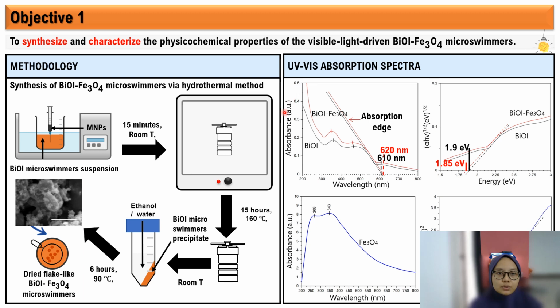This figure shows the absorption spectra of BiOI microswimmers and BiOI-Fe3O4 microswimmers. It can be observed that both microswimmers absorb in the visible light range, with band gap values of 1.9 electron volts and 1.85 electron volts. Meanwhile, magnetic nanoparticles can also absorb in the visible light range but have a higher band gap, which is 3.2 electron volts.